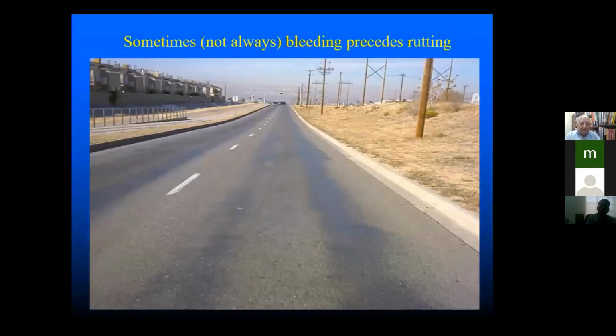Now, before I talk about rutting, let me talk about bleeding. Sometimes rutting follows after bleeding, but not necessarily. Now you can see here there's bleeding in the wheel track area. When I put down this road, maybe I put too much bitumen binder in the mix. My mix design was bad, so all the binder came up on the surface and caused bleeding.